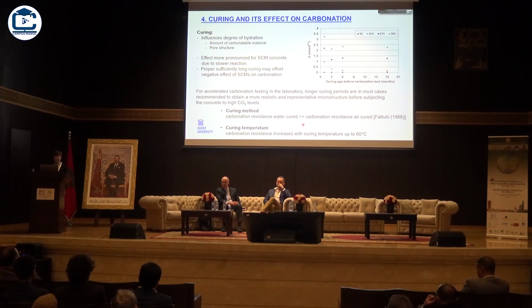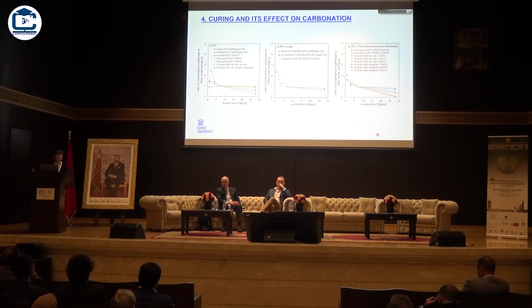What's also seen is the importance of the curing method. For instance, water-cured samples seem to have a much higher carbonation resistance than air-cured ones. And also the curing temperature, if it's increased up to 60 degrees, it also increases the carbonation resistance. So this means that if you are living in a warmer climate, this might also have an important effect, and you may not just take the results of carbonation tests at 20 degrees.